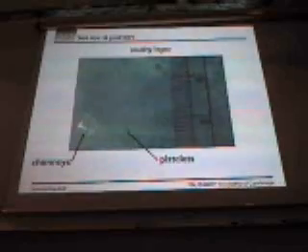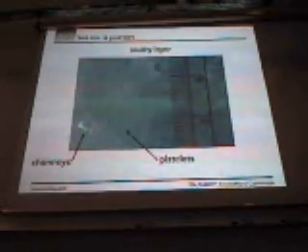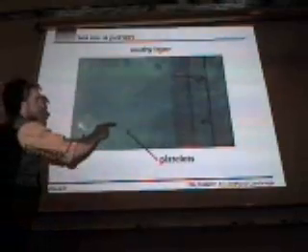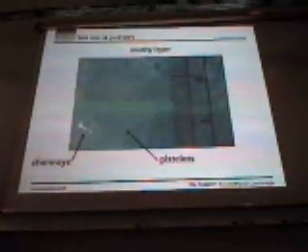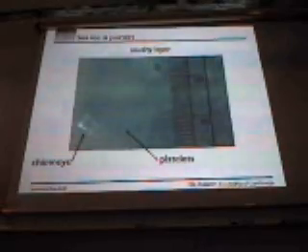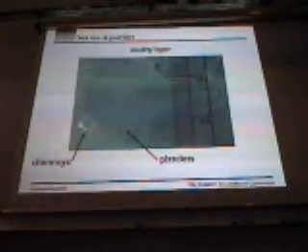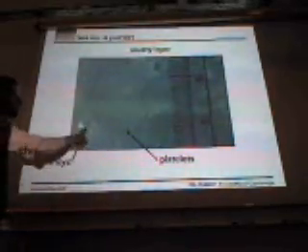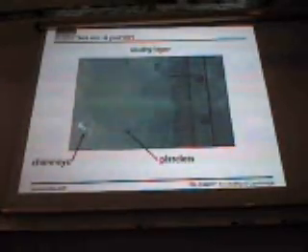Just to put this picture up from the very beginning, when you form ice from a solution which has some impurity in it, in the case of the ocean about 3.5 weight percent, mostly sodium chloride, you form what's called in the literature a mushy layer. It's a porous medium. It's got these ice crystals. You can see for ice it forms this elongated crystal with the c-axis pointing in one direction, and it's porous. It's got a liquid fraction of enriched interstitial brine, and the crystals themselves are essentially pure. There are some interesting features here already that you can see, with the length scale set by the centimeter scale over here, and we'll come back to some of these features, called chimneys, later in the talk.